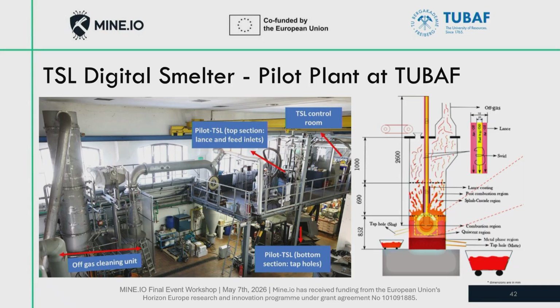We have a pilot system which was designed to handle very sulfur-rich concentrates and materials. Therefore we have a big off-gas cleaning unit, which is part of the plant and takes up most of the space. You can imagine that the top submerged lance smelter is a big hollow tube where you can insert your material and smelt it with a lance burner system, which is also introduced inside the slag to have a higher volatilization of all the materials and a big reaction surface.